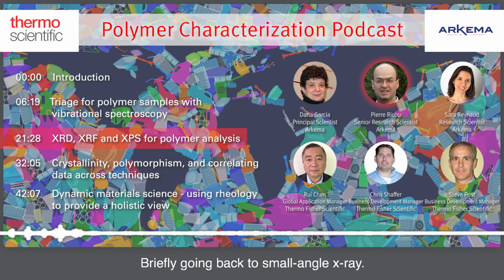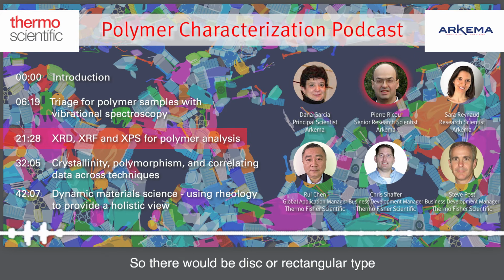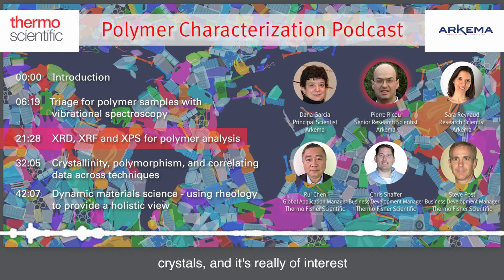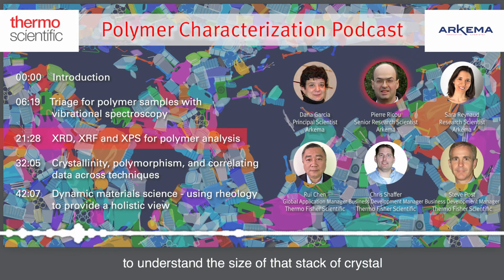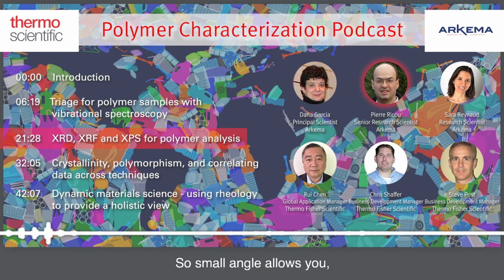Briefly going back to small angle X-ray, it brings an additional layer of information regarding the size of the crystals. In the polymer field, the way the crystals are built is that you start from a unit cell, similar to inorganic material, but those unit cells assemble into what we call lamellae. So they would be kind of like disc or rectangular type crystals. And it's really of interest to understand the size of that stack of unit cells, like how thick it is, how big it is. So small angle allows you, through the measurement of the long period and the extraction of what is called the lamellae thickness, to get an idea about those dimensions.